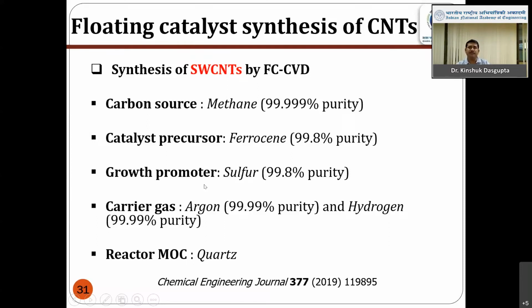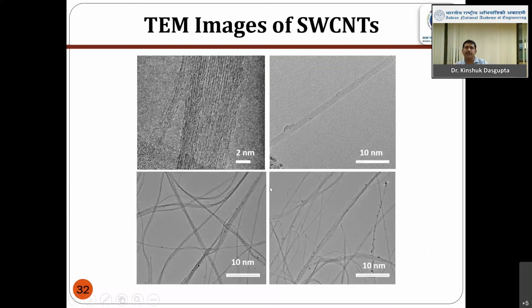One more important thing is sulfur. Sulfur is used as a growth promoter. What happens is that sulfur partially coats the catalyst particle and allows a very small portion to be used for nucleation, and that is why the diameter is small and we end up with only single wall carbon nanotube. Under TEM, you can see the single tube, but you hardly see any thickness of the wall, and generally they come in bunches. Why in bundles? Due to their very high surface energy, they try to minimize the energy and come in bundles, and it is very difficult to separate them.